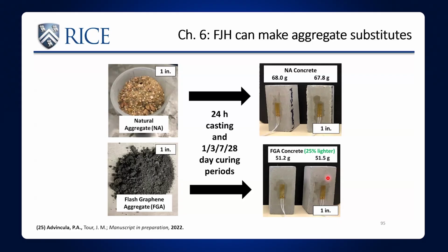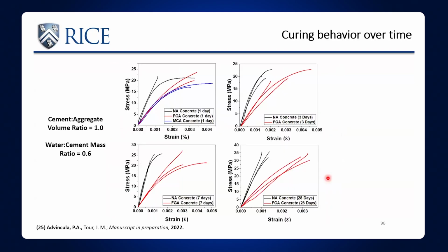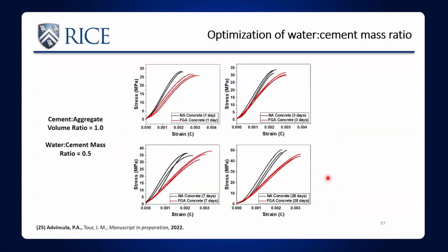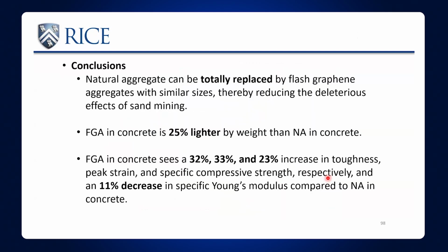But now, if that concrete doesn't work, if it falls apart, it's not any good, right? So you want to test this and test the properties. So when you went to test the properties, you look at these stress-strain curves, and you look at this at different ratios. What it comes out to be, he was able to totally replace the natural aggregate by flash graphene aggregate of similar sizes. It's 25% lighter, but you get 32, 33, and 23% increase in toughness, peak strain, and specific compressive strength, respectively. There was 11% decrease in the Young's modulus, the stiffness of the material.